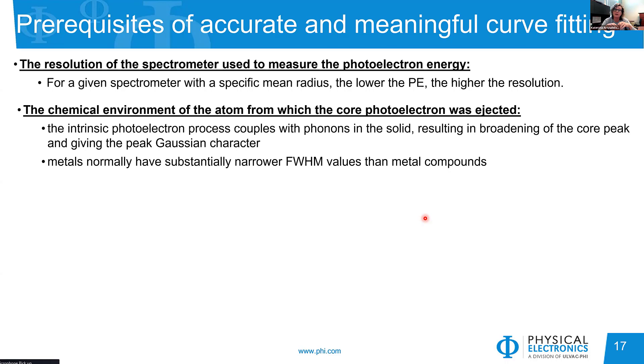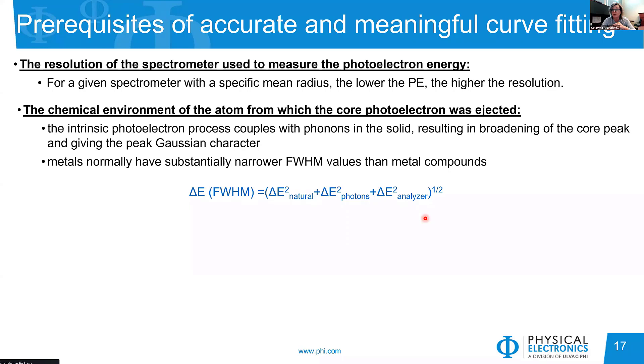There are also contributions from the chemical environment. Processes that occur when electrons interact during photo-ejection can affect peak broadening. Metals therefore have much narrower FWHM than metal compounds. In summary, the FWHM will be affected by the natural lifetime, photon source width, analyzer settings, and the element's specific chemical state — all physical processes you need to be aware of when choosing the FWHM for curve fitting.